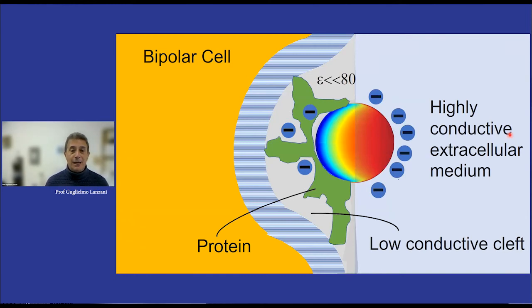So at the end, the mechanism is the following. The nanoparticle establishes a giga seal with the membrane of the cell, which is due to proteins that are forming on the surface of the nanoparticle and proteins that are extruded from the membrane. So both these fill up the cleft, and the dielectric function here is much smaller than the water dielectric function. As a result, the low conductivity means low ion concentration and no screening, so it hampers the screening. And then the electric field established by the polarization on this side can affect the protein equilibrium.